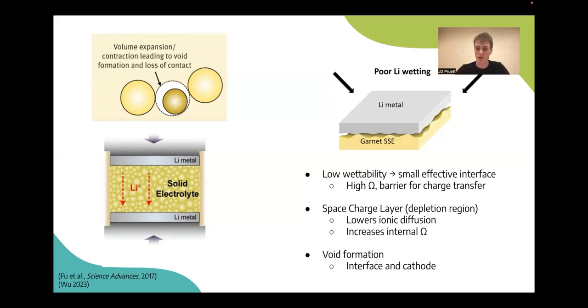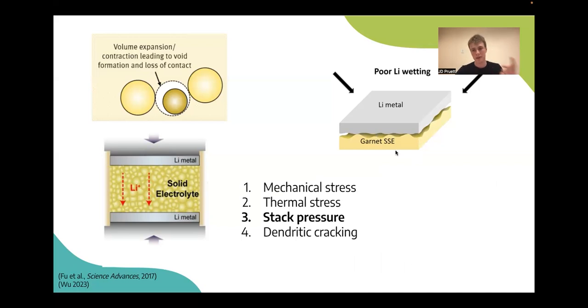But to go back to a previous slide, the issue with that is what I mentioned earlier with stack pressure. As you increase the pressure on the battery stack, you're also going to increase the likelihood and the sensitivity to any kind of mechanical stress that might cause a crack in that electrolyte. So it's a bit of a double-edged sword, where squeezing it together can reduce the wettability issue and reduce the likelihood of voids increasing resistance in our battery, but it also makes it more susceptible to cracking.